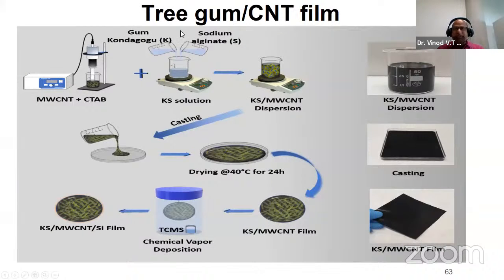So the next research is how tree gums are incorporated with carbon nanotubes. So we use the gums, and another material is sodium alginate. This is also another polymer that is plentifully available. We mixed both these polymers, gum and sodium alginate, and made the films using the casting method.